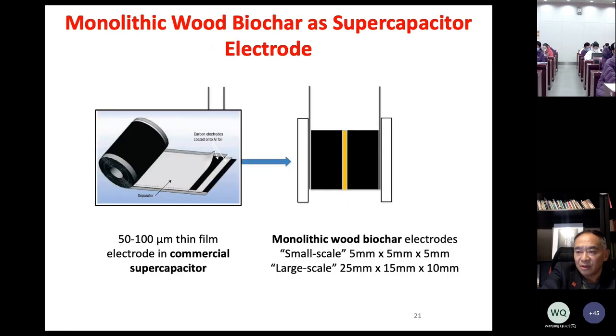So this is a comparison between a commercial supercapacitor and the cell we produce using monolithic wood biochar. What you can see here is that in the commercial one, the carbon material is a film, only about 50 to 100 micron thick, made of porous carbon powders. The reason is the high resistance of powder materials, so they have to make it very thin, otherwise the resistivity will be high and the efficiency of the capacitor will be low.